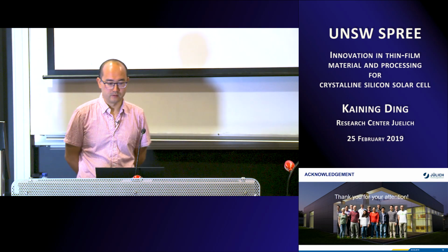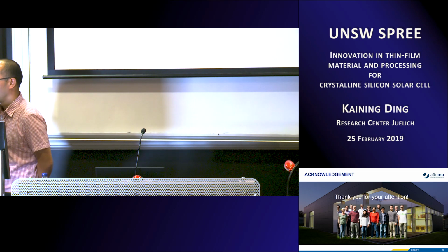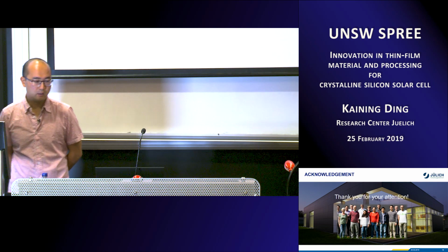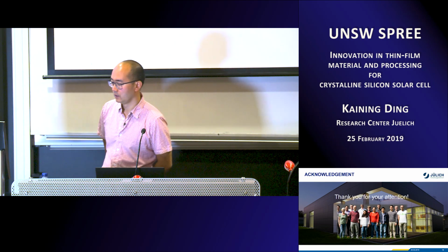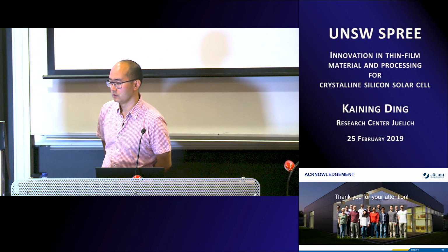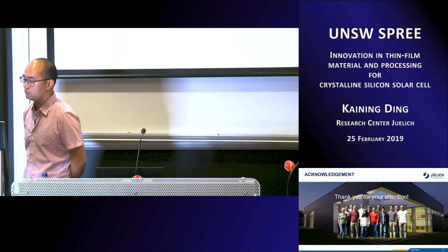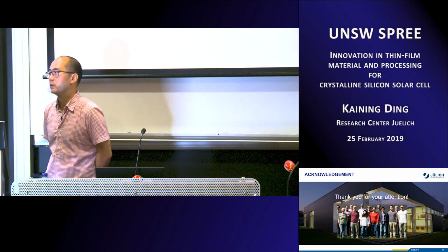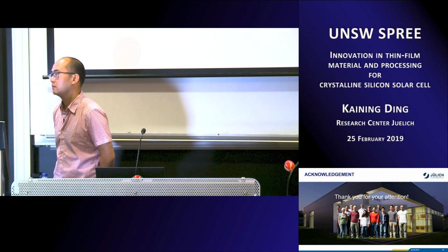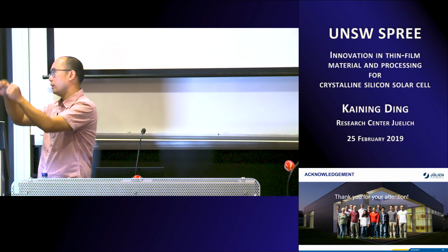But the drawback is for sure the wire lifetime. If you are making silicon, the wires will silicide during the process, and at some point they will break. I'm talking about PV. In PV, for heterojunction in particular, there is only one company, ULVAC in Japan. They sell hot wire CVD machines, and they usually promise an uptime of 2 weeks before they have to change the wires. But the changing of the wires can also be optimized. Usually you can take out the whole electrode, including the hot wire, and place a new one.